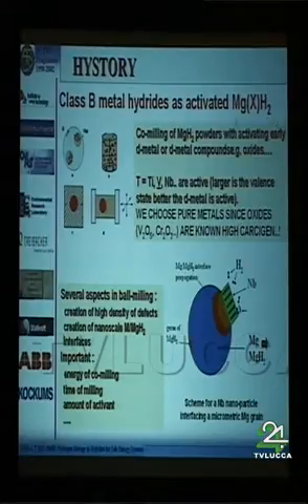The second class of metal hydride we have considered is a high temperature magnesium activated metal hydride, and for that we have considered only the possibility to activate magnesium by using metal, for example titanium, vanadium, niobium, and other types of intermetallics. Because we know that this type of oxide, for example, can be used as well as catalyst to activate the magnesium powder, magnesium hydride, but they are known also to be very toxic, and so we prefer to work with this type of catalyst. So the work was performed by using definitively the classical ball milling technique,